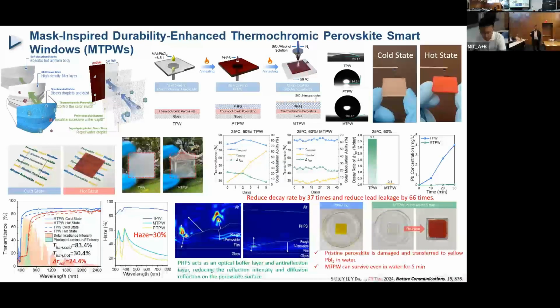With the previous perovskite materials, you can see that after 1 day, the thermochromics actually totally disappear. And maybe after 5 days, there's no thermochromics effect. However, after adding these 2 layers, we can extend the lifespan by up to 1 month. So this is one of the greatest achievements of our work, to identify how we can extend the lifespan of the perovskite material such that in the near future it can be put to commercial use.